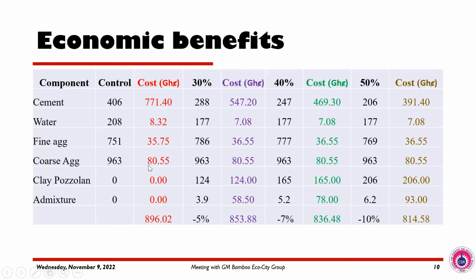Now, what we did was that we looked at the costs per meter cube and the cost of producing a C30 concrete. I got 896 Ghana cedis. Now, I did 30% clinker reduction or cement reduction, replacing it with a clay pozzolana. And I reduced the cost by 5%. So I had 853. Now, at 40%, I reduced the cost by 7%. At 50%, I reduced the cost by 10%. That is very important. One of the most important things I want you to note is this one.